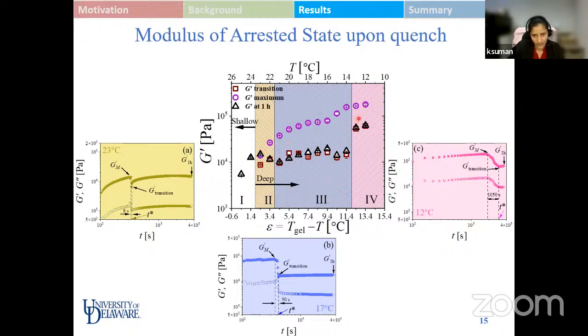This is quite expected because as we go deeper and deeper into the temperatures, we are entering into the more arrested regions, which can be manifested by the increase in the modulus value. Specifically, the G prime maximum value goes on increasing quite evidently, as opposed to the G prime transition and the G prime at the end of aging study.